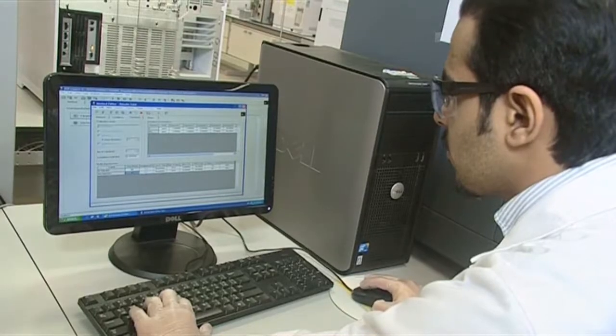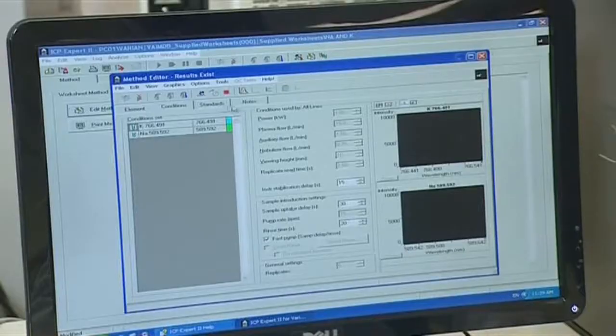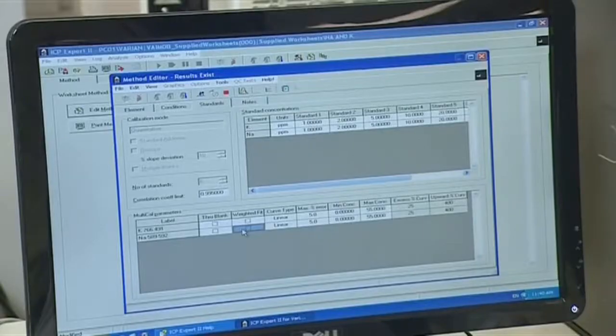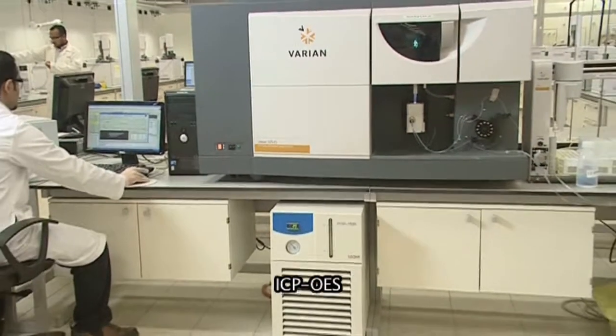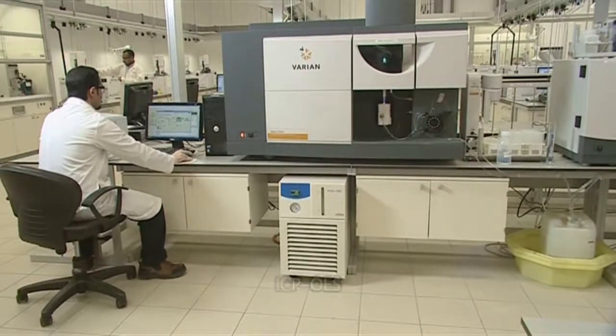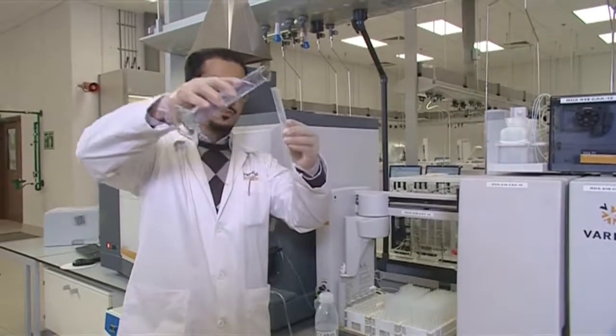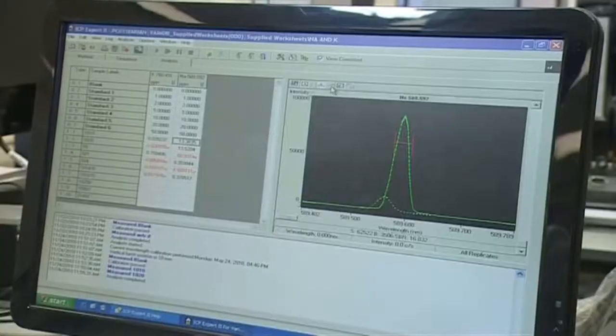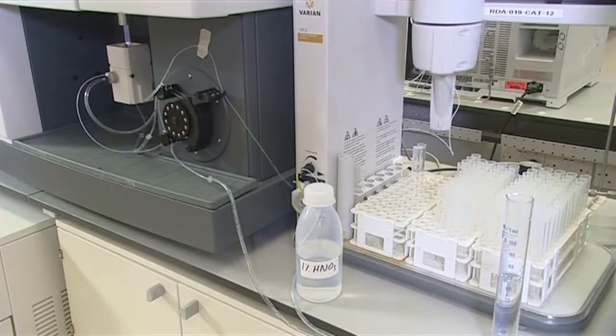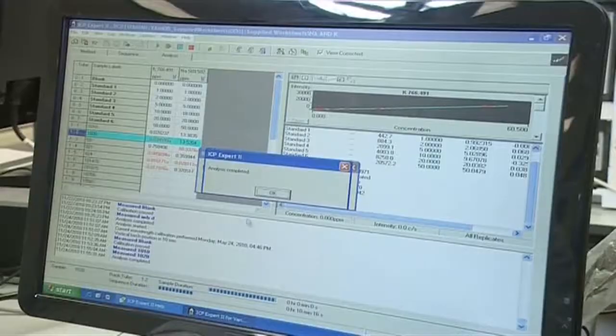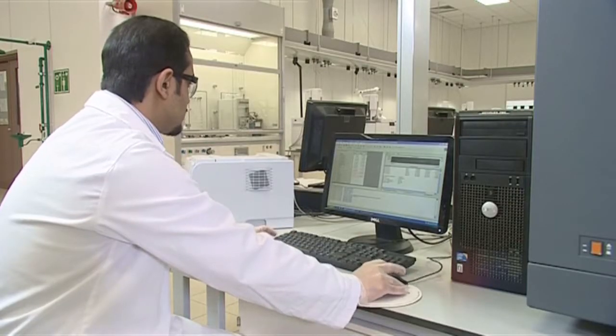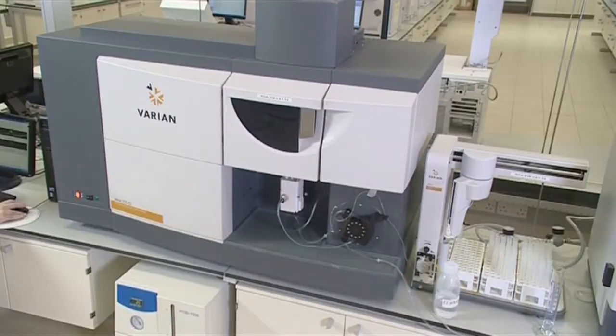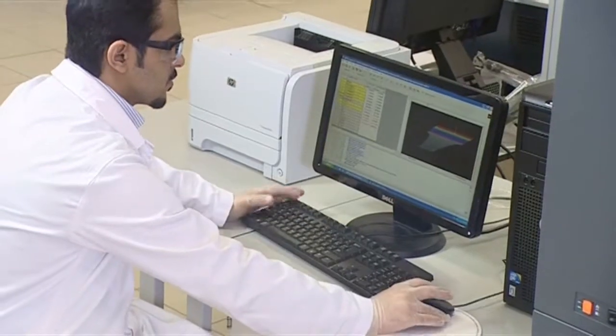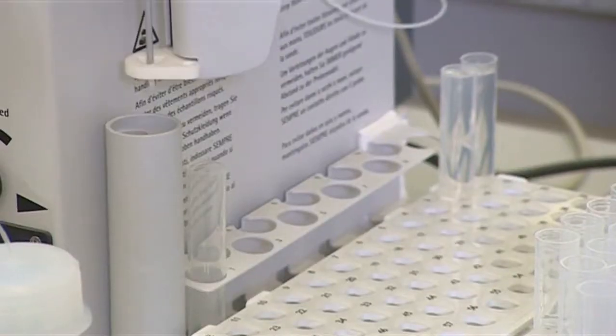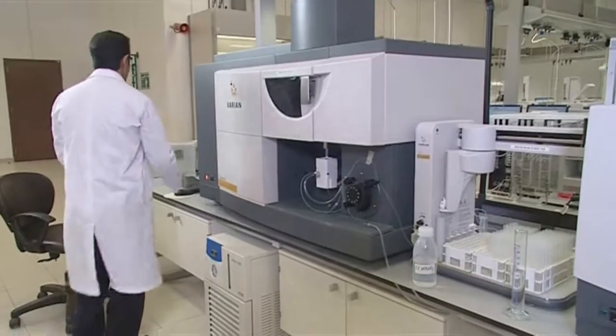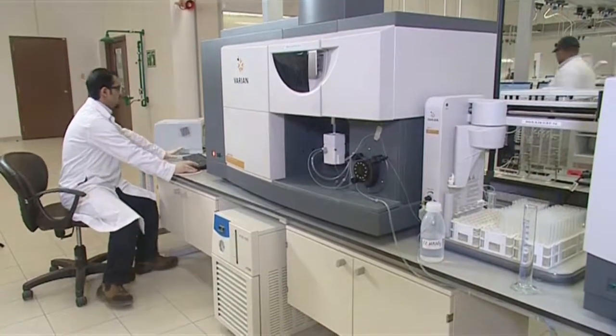Saudi Kayan Quality Assurance Department has two Varian 725ES ICP OES for determination of trace level of metals in sample matrix. Prepared sample solution is introduced into the core of inductively coupled argon plasma, ICP, by autosampler, which generates temperature of approximately 8,000 degrees Celsius. At this temperature, all elements become thermally excited and emit light at their characteristic wavelengths. The results are calculated against standards and can be measured up to ppb level.